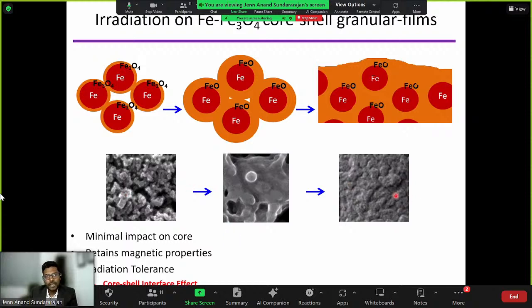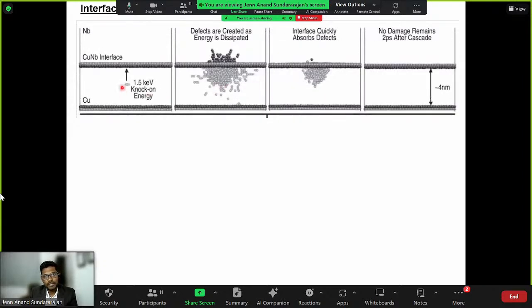One thing about the interfaces: let's take two different materials, niobium and copper. When you expose them to radiation, they form a huge number of defects. This is a simulated one, and it absorbs. This is from a different study, and eventually everything disappears. This is about 2 picoseconds after the cascade, a really short period of time. So the interface plays a huge role, right?